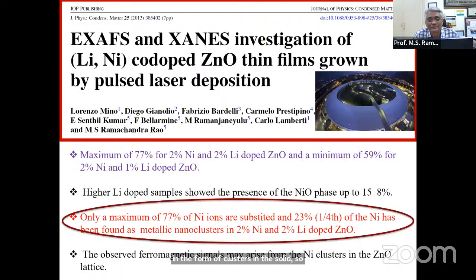This was a very interesting work. My colleague Carlo Lamberti, an exciting scientist from Italy, passed away unfortunately a few years back. But what we showed was, even though X-ray diffraction shows that nickel actually goes inside the lattice, only 77% gets substituted, and the remaining nickel is there in the form of nanoclusters. So the magnetism you see is all because of these nanoclusters. It's not true magnetism.